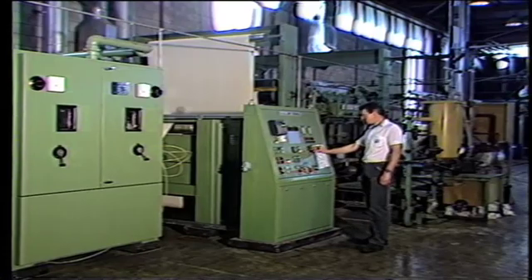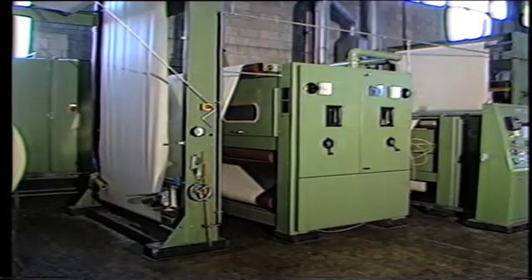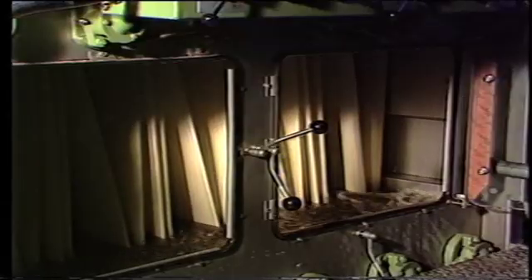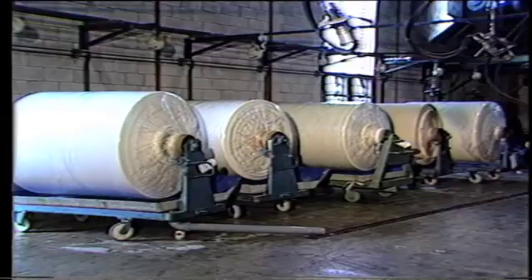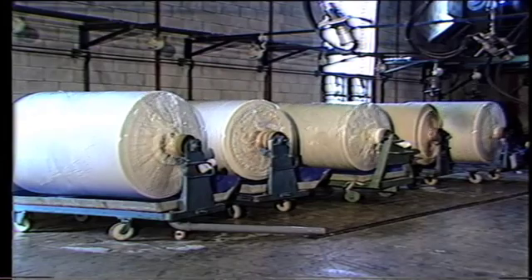After cropping, many fabrics pass to the singer desizer machine. In the first cabinet, the singer removes short surface fibres and any remaining dust by passing the fabric over a gas flame. The second cabinet can be used as a quench tank to dampen and cool the singed fabric. Desizing can also be carried out in it. This process breaks down the size, the substance that has been added to the cotton to strengthen it before weaving. Once the desizing chemical has been absorbed into the cotton, the cloth is rotated for 16 hours for the chemical to react with the fabric and break down the size.